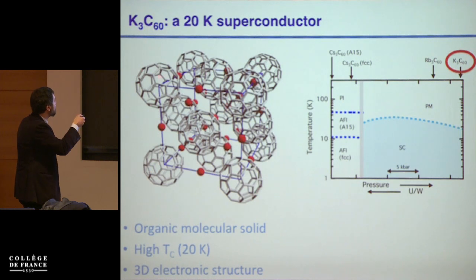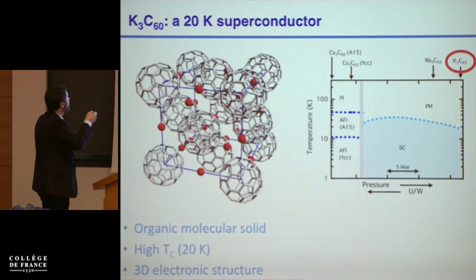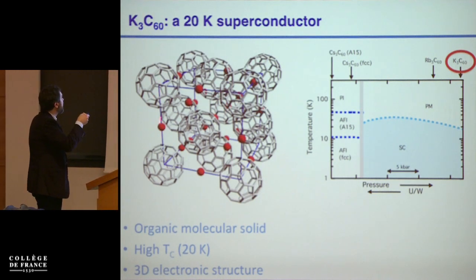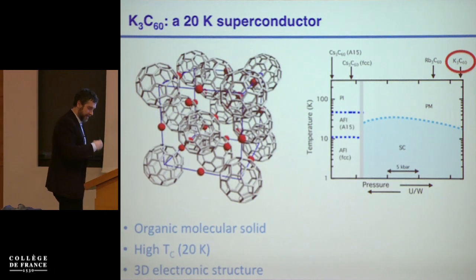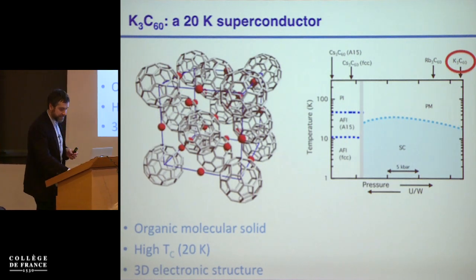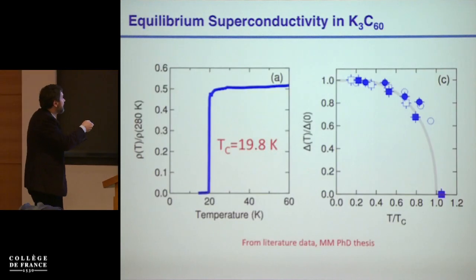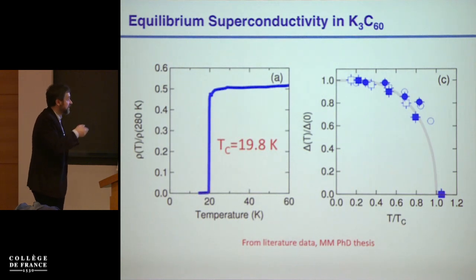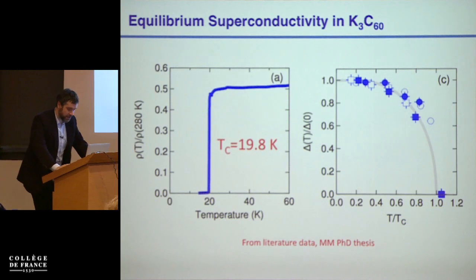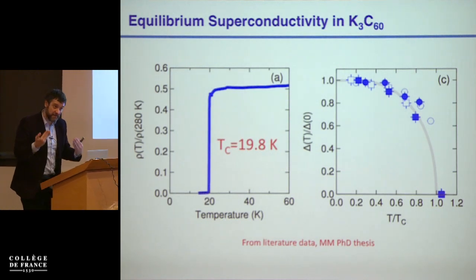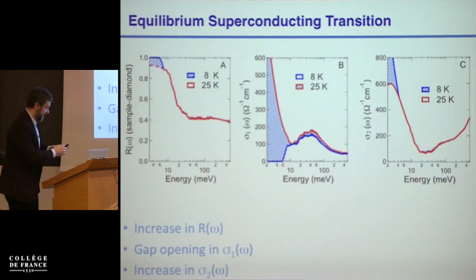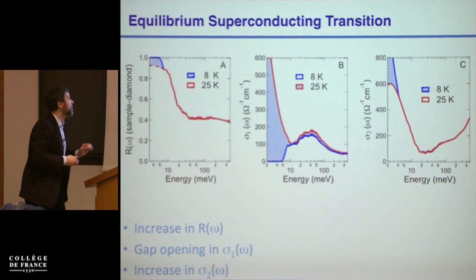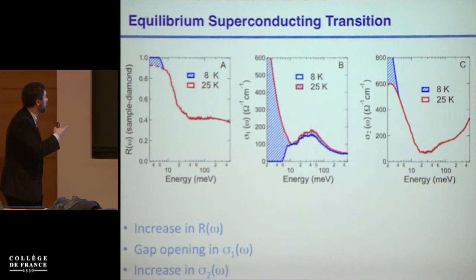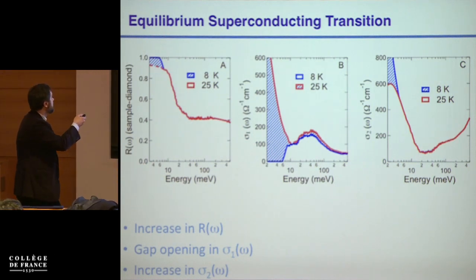It's an FCC lattice of buckyballs, which are doped 3 times by 3 potassium atoms. And so one has the physics of this FCC lattice of 3 times doped buckyballs that become superconducting at 20 Kelvin. Okay, so this is observed, for example, statically by measuring conductivity or by measuring the size of the gap, which follows a very nice mean field behavior. If one wants to look at AC features of the superconducting state, one can look, in some crystals, which are the ones that we're going to be using, at the optical properties of these powders of potassium 3C60.